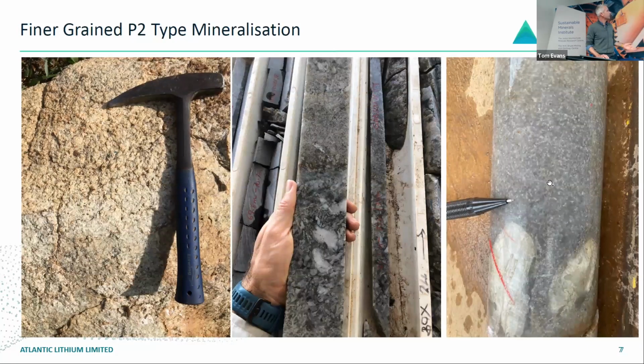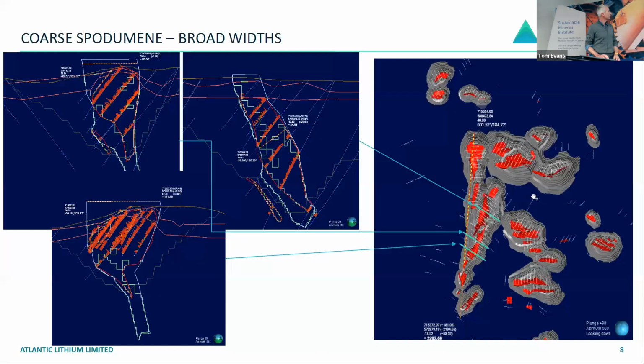But from a processability point of view, this is much harder to process to a saleable concentrate than the coarse-grained material. And depending on how much of that you got volumetrically would really dictate how you have to process the material going forwards. If you go into flotation, it's at a much higher cost, or you can still generate a saleable product through a dense media separation circuit.